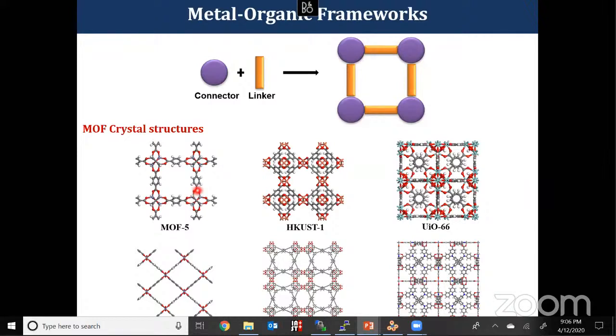As well, very recently, people are using high throughput screening as well as machine learning applications. In that, they will have different connectors, different linkers, and connect them in different ways. By using these techniques, they will produce more than 10,000 or 20,000 MOFs, and they will screen the MOFs according to their properties based on surface area, pore volume, density, and available pore geometry. So they will cut down the number of MOFs by physical-chemical property. Finally, they will end up with less than 100 MOFs and suggest that experimentalists directly synthesize these MOFs, and the experimentally synthesized MOF results as well as the theoretically modeled MOF results both align with each other.